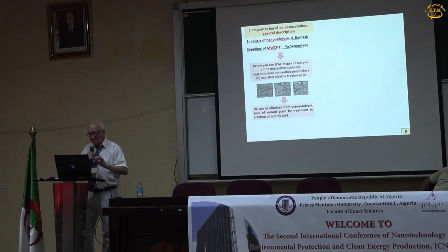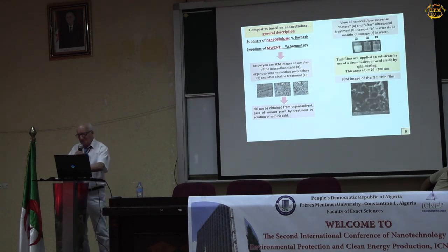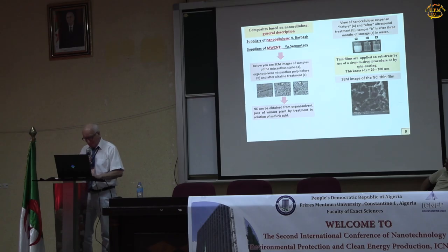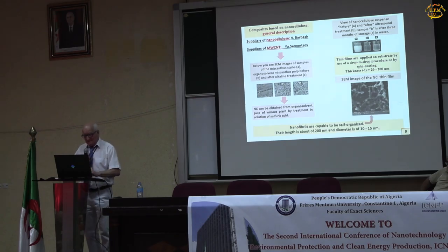In our experimental study, we used the nanocellulose produced by Valery Barbash at the National University Kyiv Polytechnic Institute and multiwall carbon nanotubes provided by Yuri Sementsov, he is here. Below you see images of the sample, miscanthus, organosolvent pulp before and after alkaline treatment. Also you see the suspension of this nanocellulose and the images of a self-organized film of nanocellulose on the substrate.